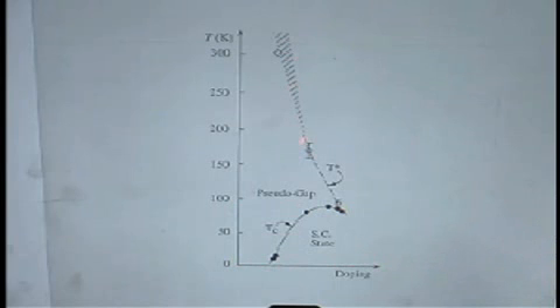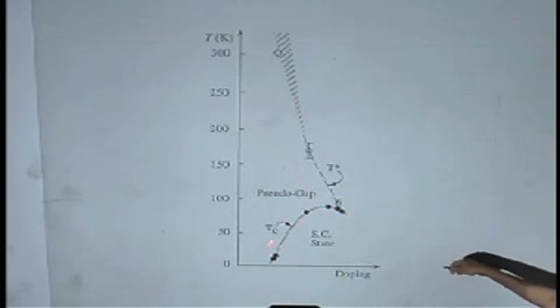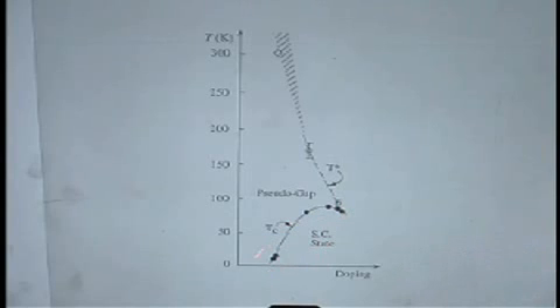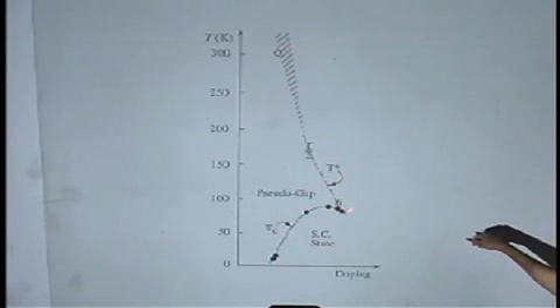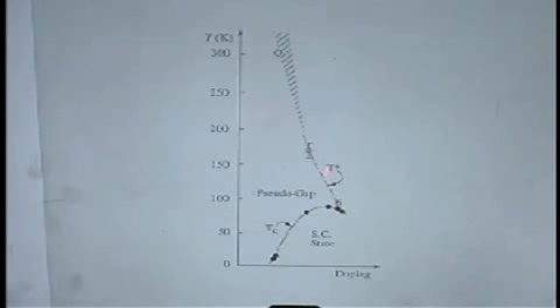And what is interesting then, in this system, you get a new phase here, which is called a pseudo-gap phase, where you identify a crossover temperature. This is a sharply identified temperature which is associated with a phase transition to a superconducting system, whereas this is a less defined temperature. You see this is a shady area, and these error bars are larger because this is really a crossover temperature. What happened there?